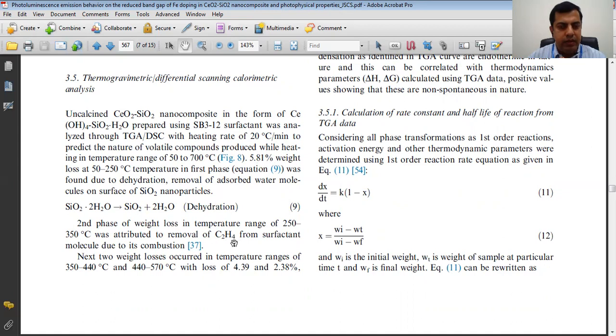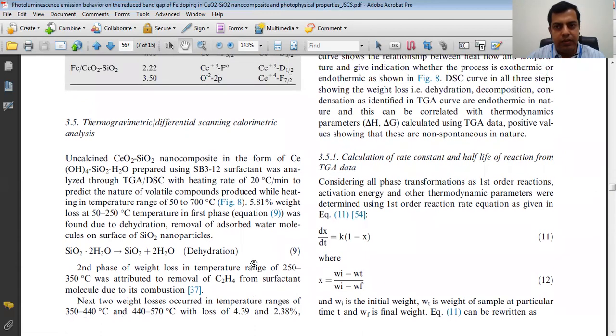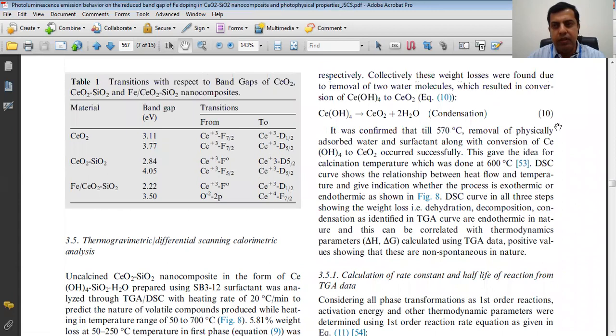The second phase is due to the removal of C2H4 from the surfactant molecules. The third phase weight loss is 350 to 570 degrees, which is also due to the removal of water. This is due to the condensation process because here the cerium hydroxide is converted into cerium oxide. So this is how you can characterize your nanomaterials by using thermo-gravimetric analysis.